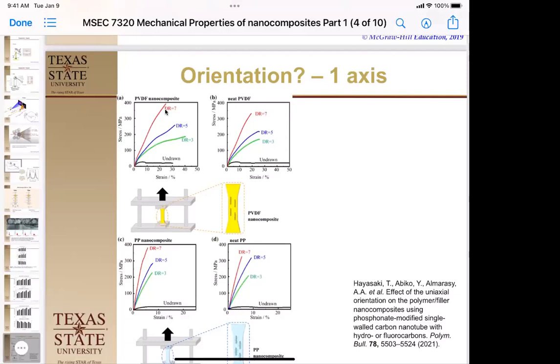What is the, in the graph on the right, is it neat polypropylene? Yeah, this is polypropylene, no nanomaterial in it. This is polypropylene with the modified carbon nanotube. So what we see here is if you look at the modulus and the ultimate strength, the nanocomposite materials are 10 to 50% higher than the neat polymer by itself using the same process. So it's tougher, it has a higher modulus, and it has a higher ultimate strength. That's right where it breaks, so it actually has a higher ultimate strength.